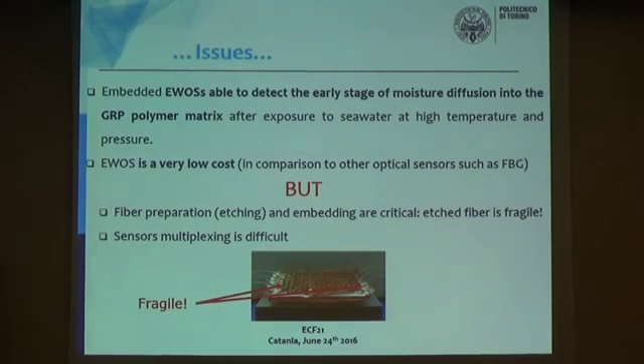Okay, so this basic way to sense the water diffusion works, and it's also low cost because the sensor preparation is very easy. You basically etch the fiber, but there are some problems. First, etching and embedding are critical because you must etch the fiber somehow into the middle and later embed it. The etched fiber is only 60 micron thick, and it's very fragile, very easy to break, so one must be quite skillful to do this operation. And as I said before, you have one input and one output, so multiplexing is difficult.